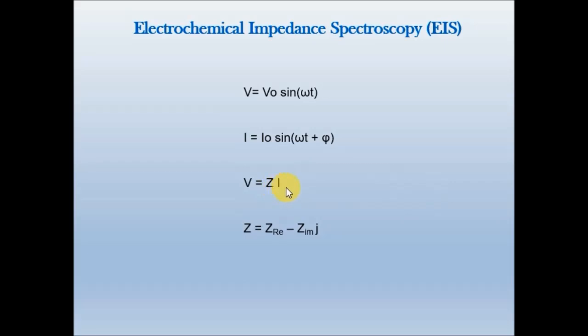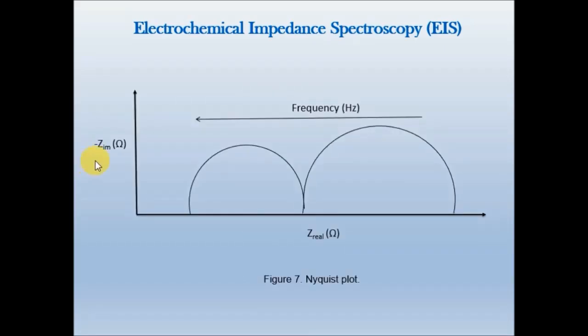The impedance is a complex number. When the imaginary component of the measured impedance is plotted versus the real part, the spectrum in a Nyquist plot format is obtained. Ideally, a series of semicircles is obtained, and each of those semicircles can be ascribed to different components of the system. By impedance spectroscopy, signals of the electrolyte and the electrodes can be resolved or separated, and the total impedance of the sample, indicated now, could be read at the intercept of the spectrum with the horizontal axis, at the very right of the Nyquist plot.